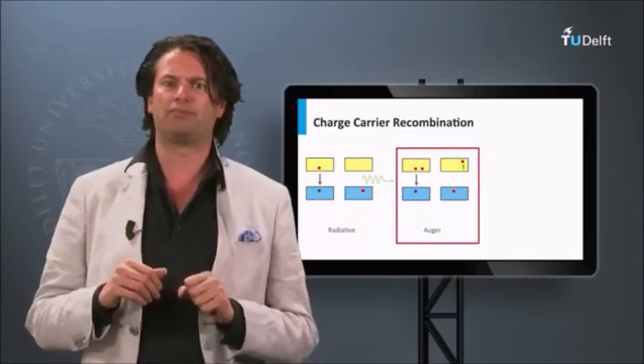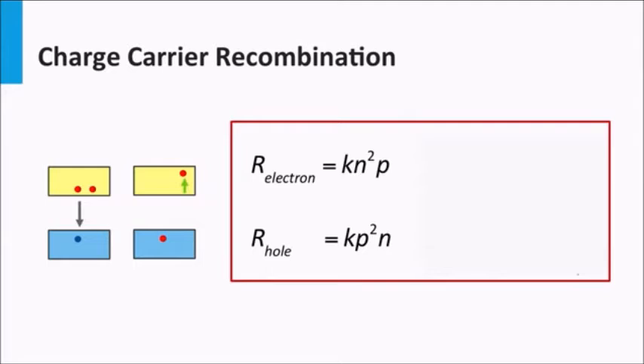Let's consider Auger recombination. Auger recombination is the process in which the momentum and energy of two recombining hole and electron is conserved by transferring energy and momentum to another hole or electron. This electron is excited in higher levels in the electronic band. This excited electron relaxes again such that the energy is lost as phonon modes. Phonon modes are lattice vibration and is nothing different than heat. As the recombination process is a three-particle process, the Auger recombination rate expressed in R is strongly dependent on the charge carrier densities. N is the density of electrons and P is the density of holes.